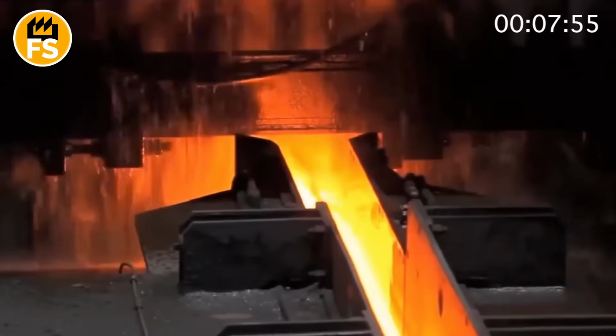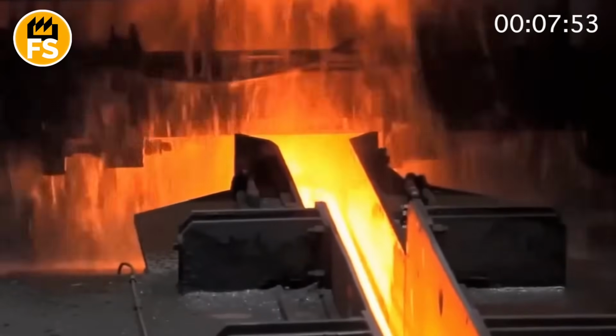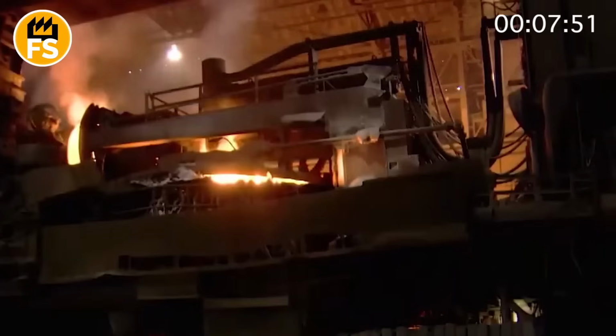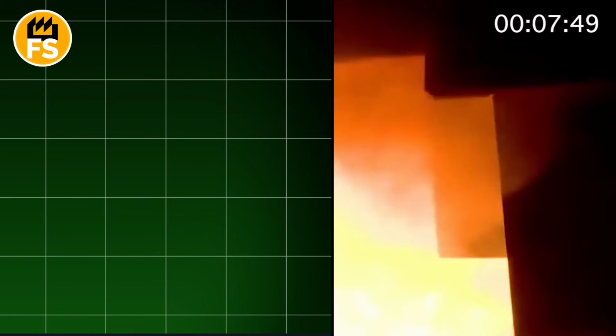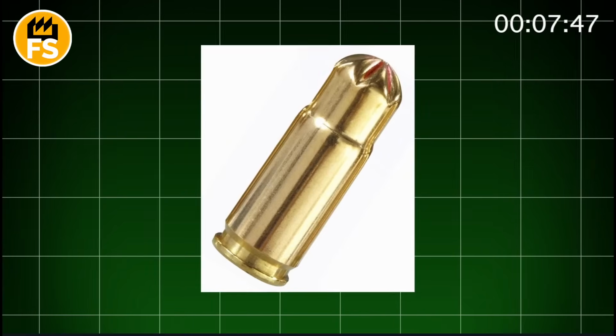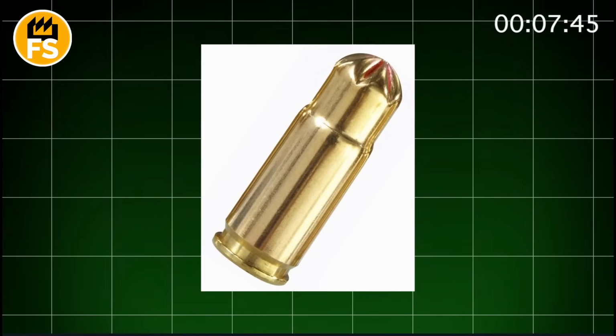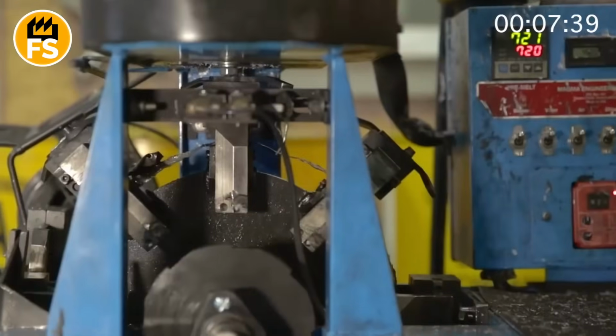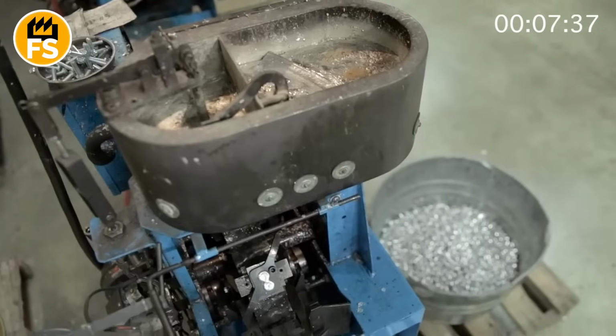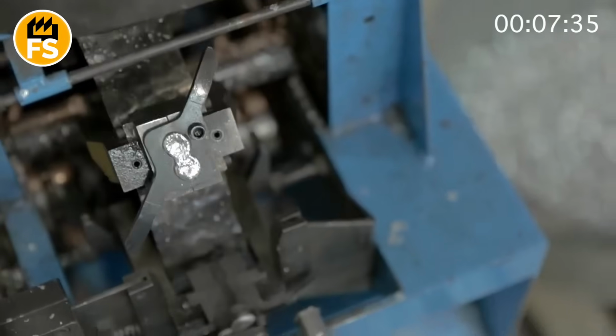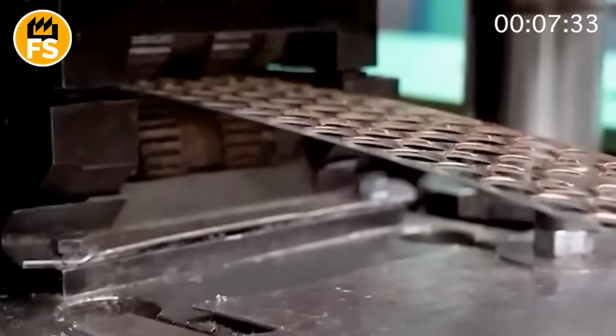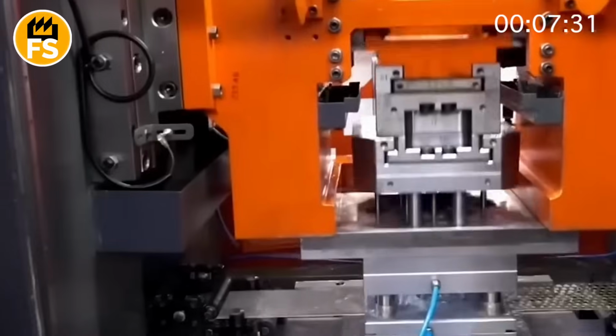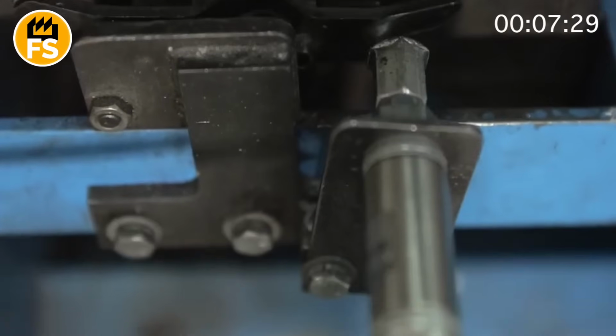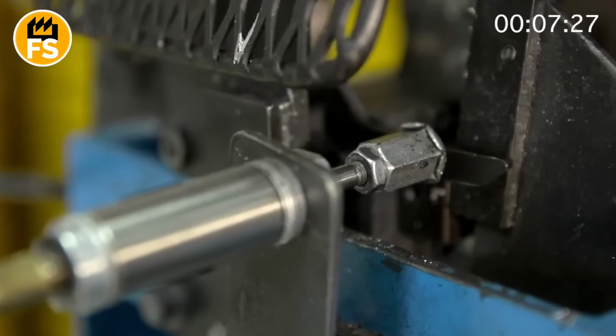Next, the brass sheet is fed into a press line, a high-speed stamping press that, with lightning precision, punches out small discs, so-called blanks. Their diameter is approximately 0.75 inches, and their thickness matches the original sheet. The press operates at up to 250 strokes per minute, so every second yields a new batch of blanks. The resulting discs are heated to 800 degrees Fahrenheit. This is necessary for the subsequent deep drawing process.